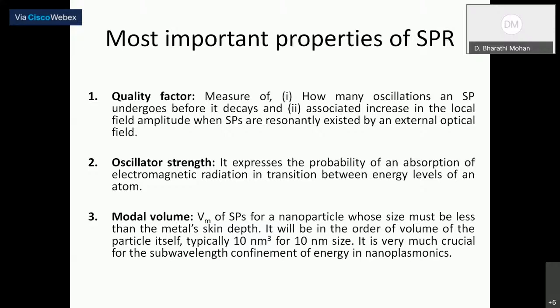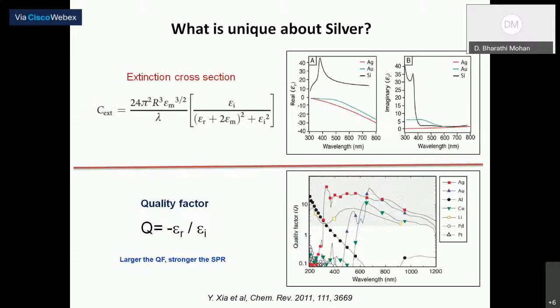It is nothing but Vm of the surface plasmon for any nanoparticle whose size must be less than the metal skin depth. It will be on the order of the volume of the particle itself, typically say 10 nanometer cubed for a particle with a size of about 10 nanometers. And the mode volume is very, very crucial for the sub-wavelength confinement of energy in nanoplasmonics. So what is unique about silver?